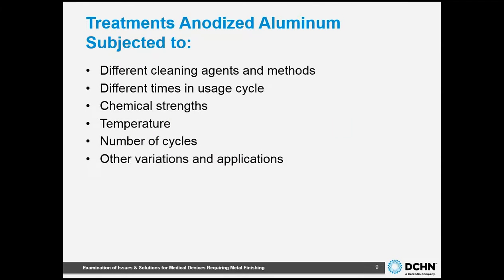So I want to take a moment to discuss what we at DCHN have learned about cleaning and sterilization in hospitals and clinical environments. What we found was that regardless of the cleaning method or recommendations by the manufacturer or chosen by the hospital, there are significant variations in the protocols used. For instance, there are many different cleaning agents, and they are used at many different strengths, temperatures, times, and number of cycles. Add to that the different equipment and staff preferences, and there can be any number of variations to what the device sees as it is cleaned and sterilized.